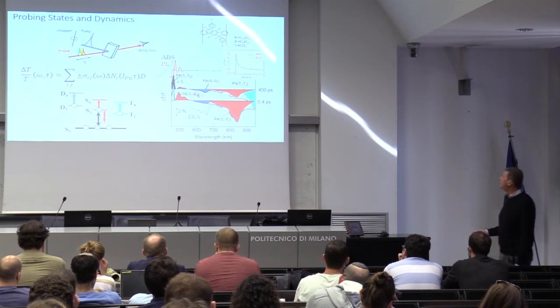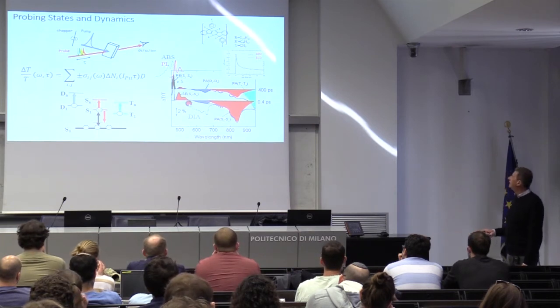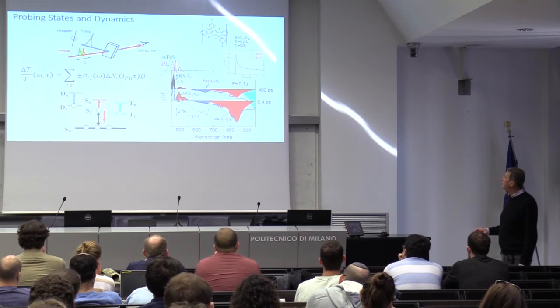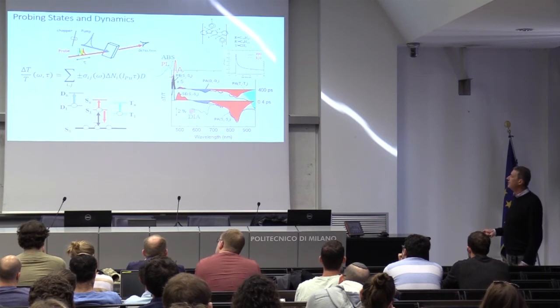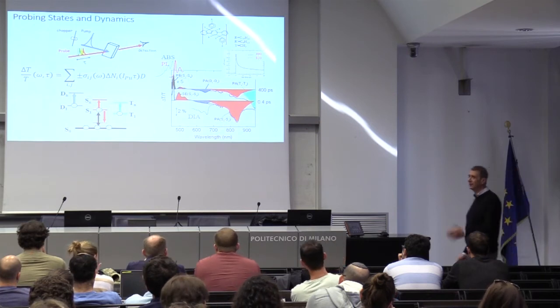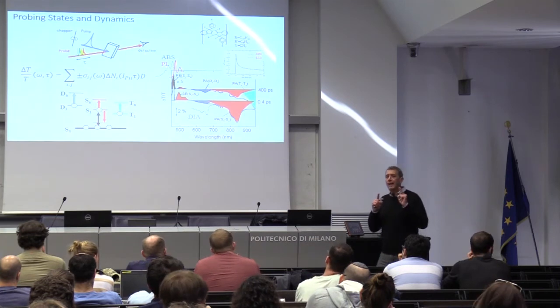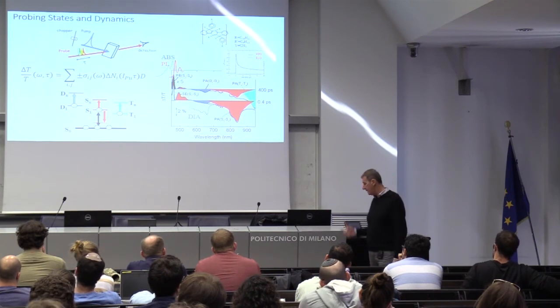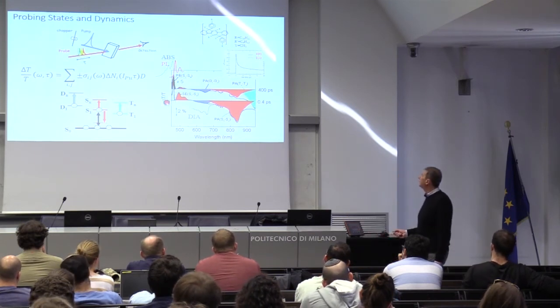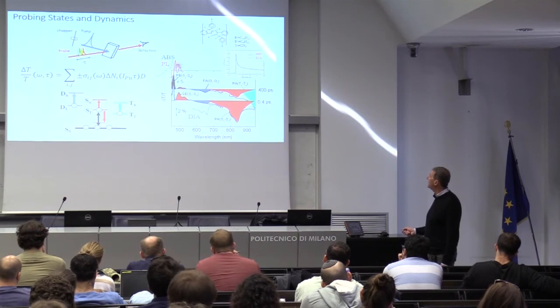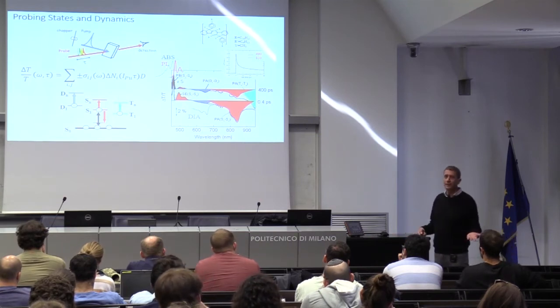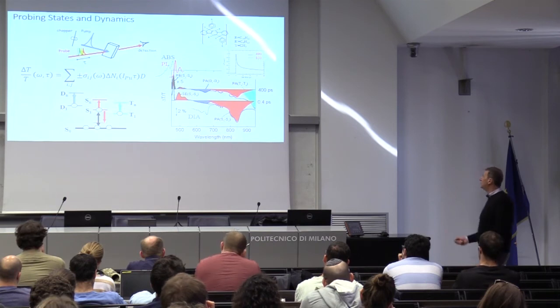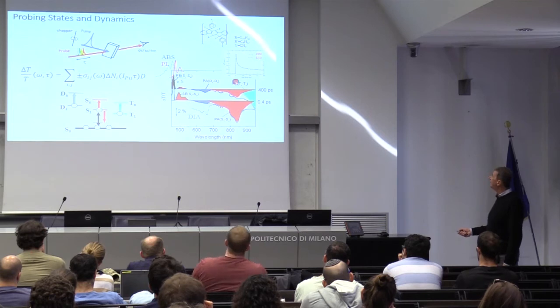other states. Then you see two in red, two features. This is a positive peak, and this is a negative peak. And now this is in wavelength, so this looks much broader than this. Actually, they are comparable because it's wavelength, not energy. Now, these two are stimulated emission and photoinduced absorption from the singlet state. How do I know? Number one, this spectrum here overlaps with photoluminescence, and stimulated emission should look like photoluminescence. Number two, this state here and these two spectral features have the same lifetime.